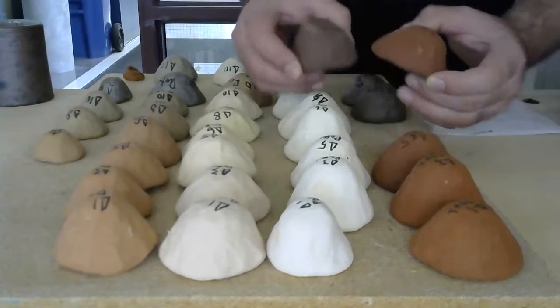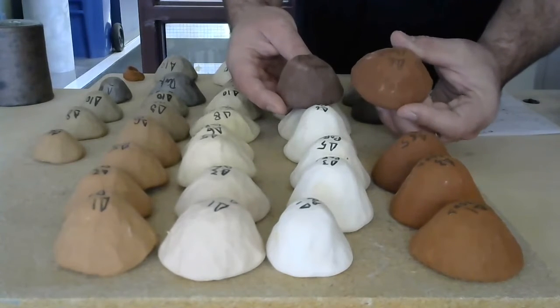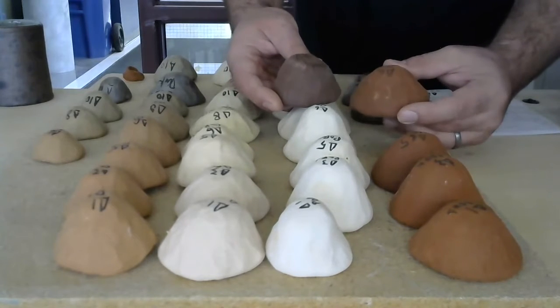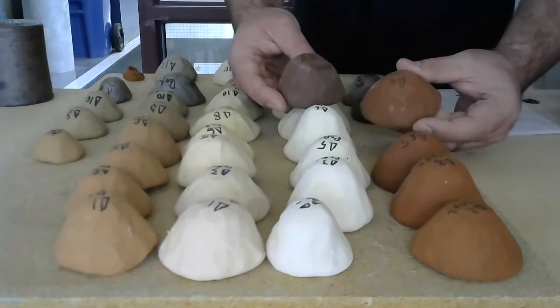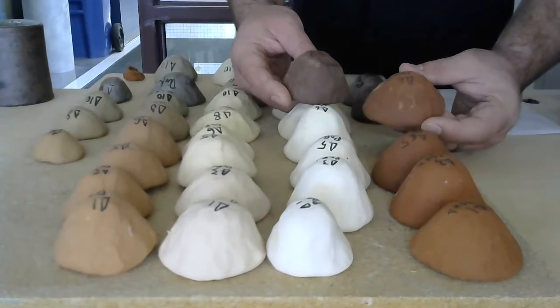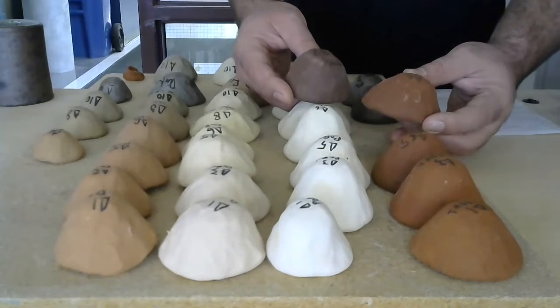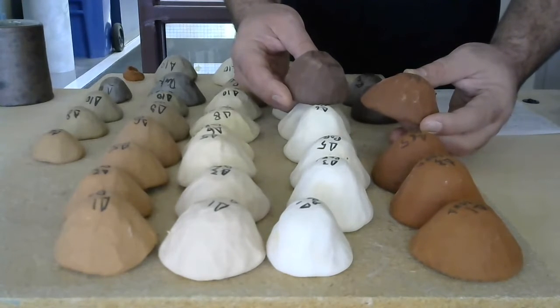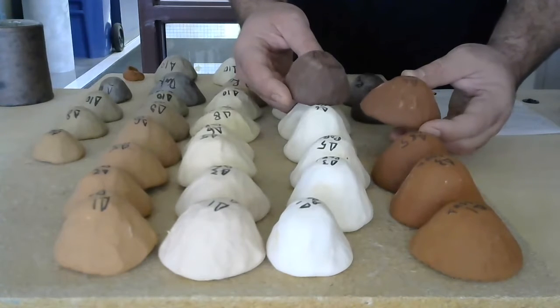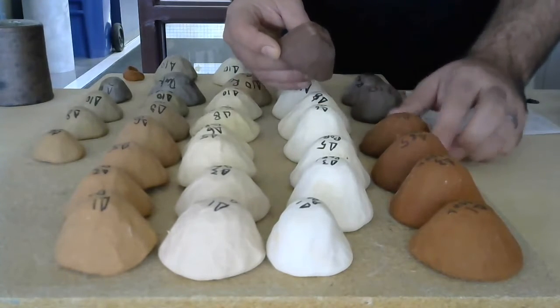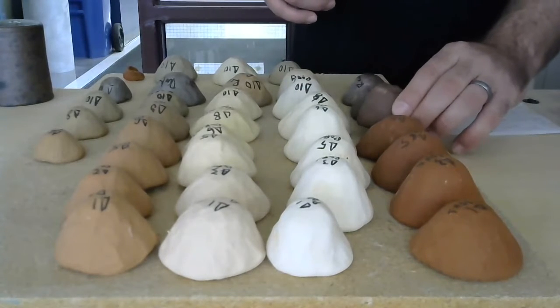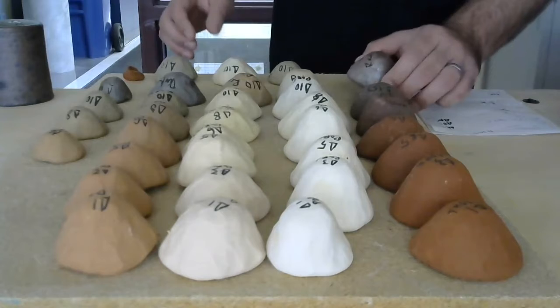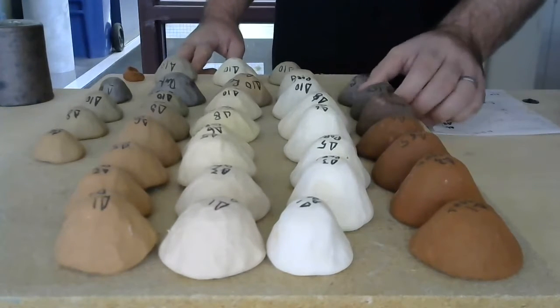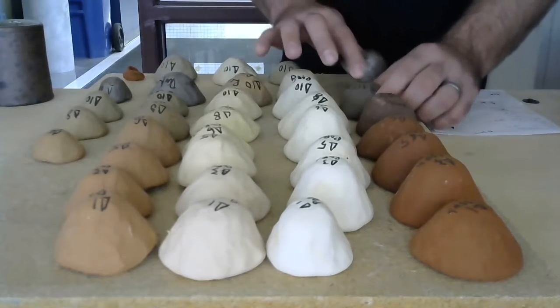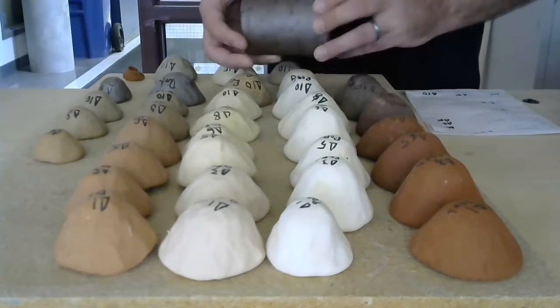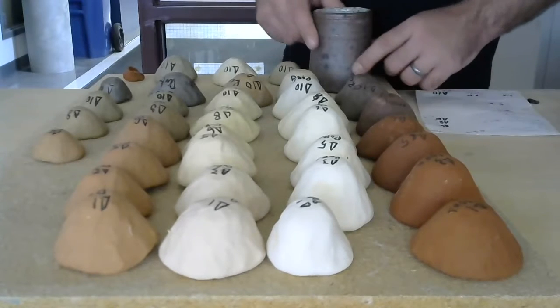So one really notable difference is between cone 6 and cone 8 when things start to flux out. And typically iron will flux out around cone 4 to cone 6, which is around 2150 to 2200 degrees Fahrenheit, right? So the interesting thing about the clay body that I dug in that creek bed is that it's pretty stable even at high temperature, which is really kind of exciting, because without even processing it through a sieve, it turns out really nice with this cup right here, right?